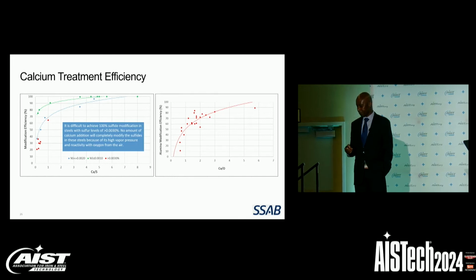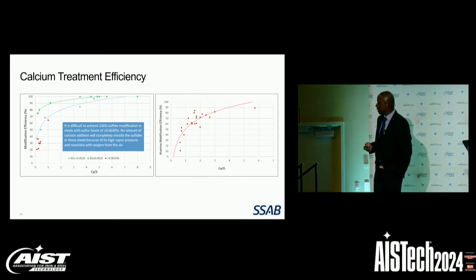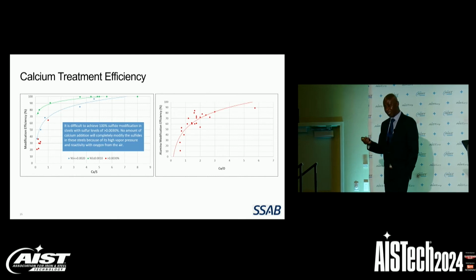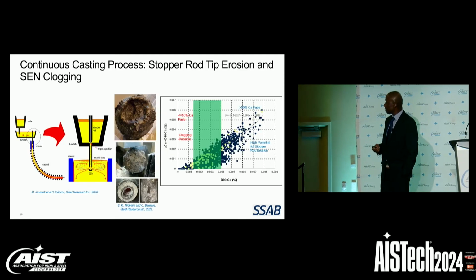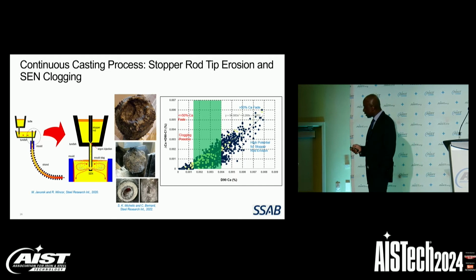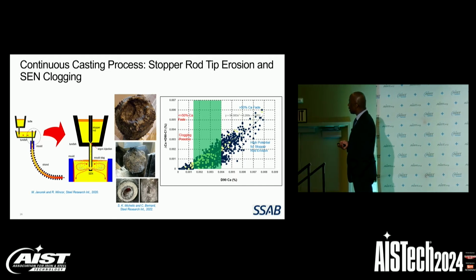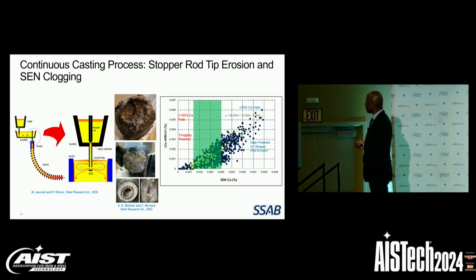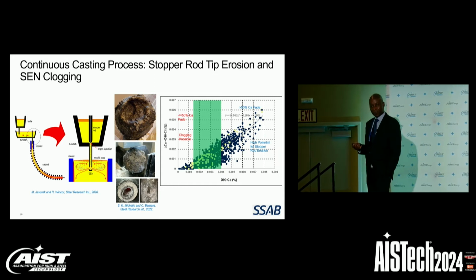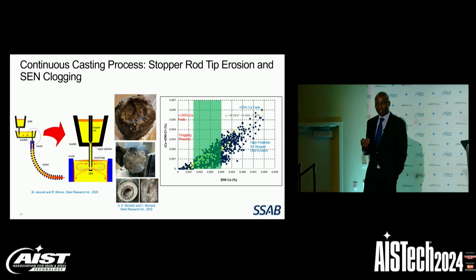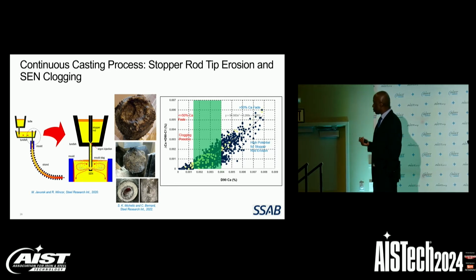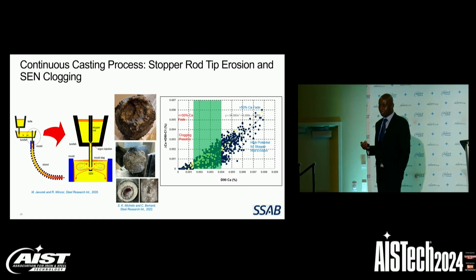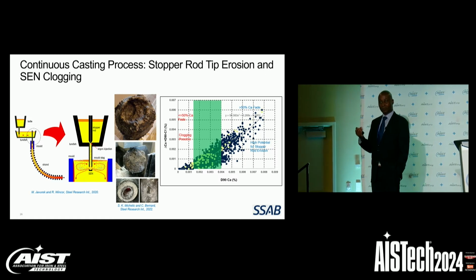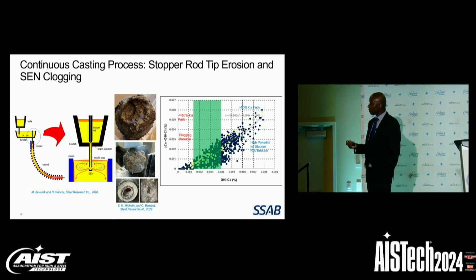We also found that if the sulfur content is higher than 30 ppm, it is impossible to completely modify the sulfide inclusions. So at the end of refining, once refining is complete, the ladle is sent to the caster for casting. At the caster, the steel flows from the ladle into the tundish and then into the mold where it begins to solidify. As the strand solidifies, it is gradually withdrawn away from the mold. The withdrawal speed of the strand should be consistent with the flow of liquid steel from the ladle into the tundish and from the tundish into the mold.